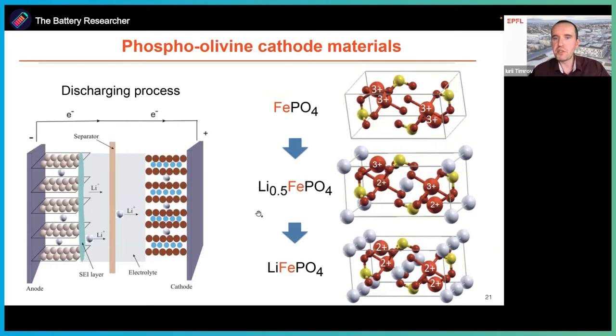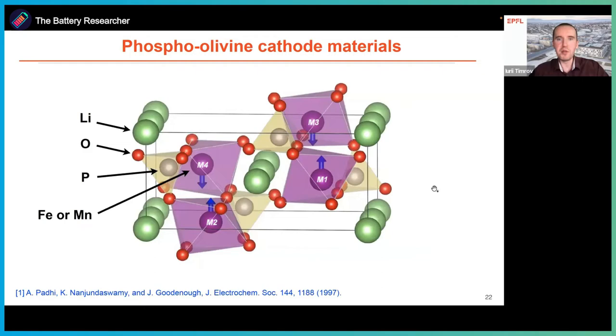So this is to give a bit more details on how we simulate this. This is the simulation cell for the phospho-olivine. We have four formula units. In green, we show lithium, oxygen in red, phosphorus are in these tetrahedra, and we have four octahedra, in the centers of which we have either iron or manganese or both. So we consider three cases: just iron or just manganese, or 50% manganese and 50% iron. And the material is antiferromagnetic. So with these arrows, we indicate the orientation of spin, and it is insulating, as is known experimentally.